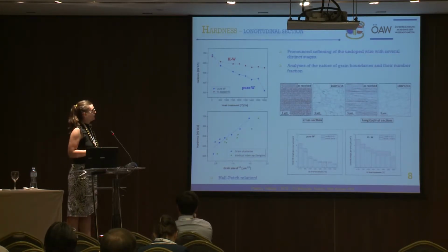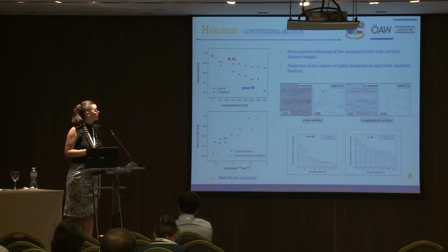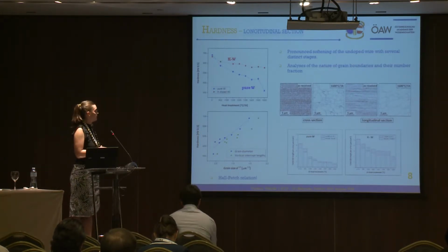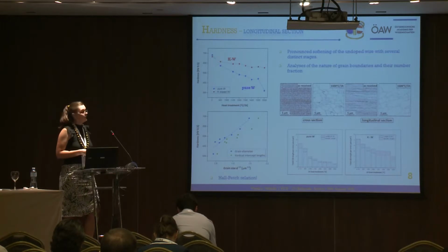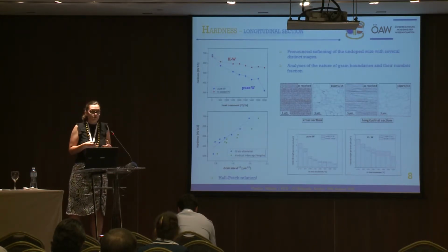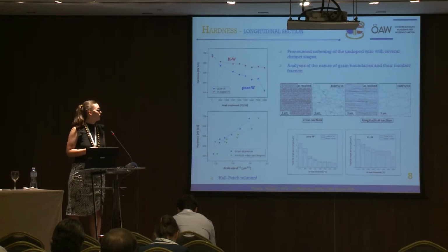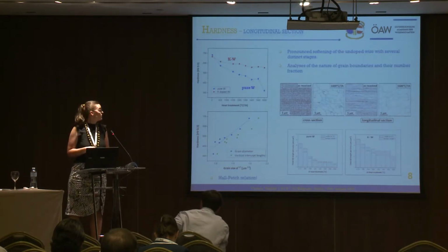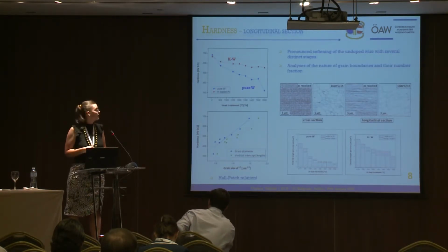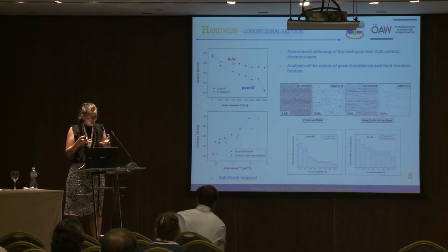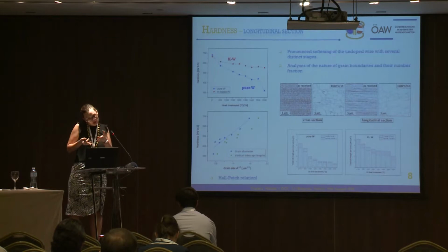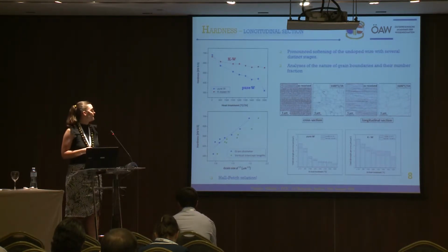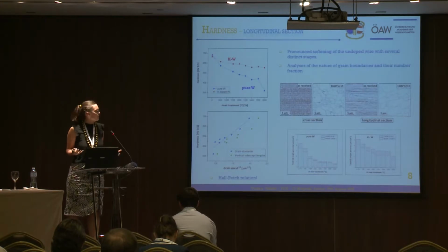One was analyzing the grain boundaries. So here you can see the grain boundary map in cross-section and longitudinal sections. Here we wanted to look at how the amount, or total length, of grain boundaries decreases with annealing temperature, but also at the nature of the grain boundaries, whether they are low-angle or high-angle grain boundaries, and the number fraction in each annealing treatment, how it changes over all the various annealing states. All of this gives us information that complements the discussion about the different annealing phenomena that take place.